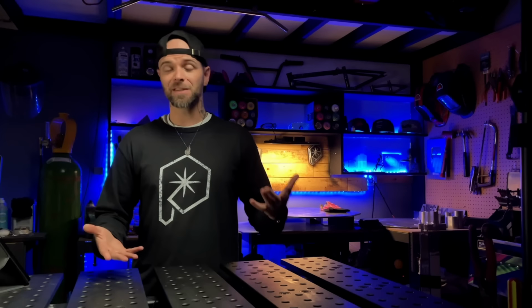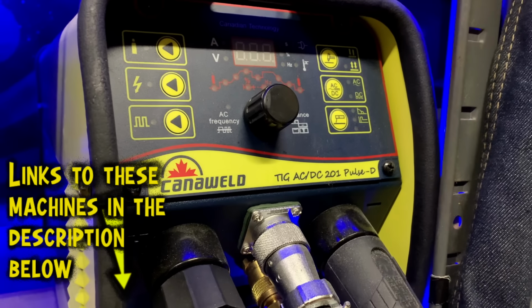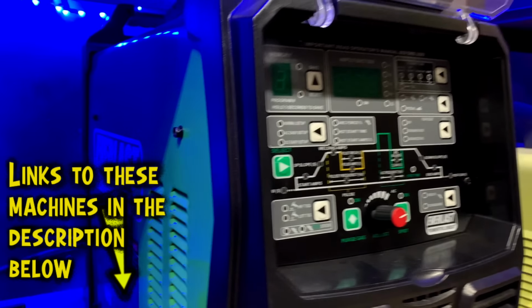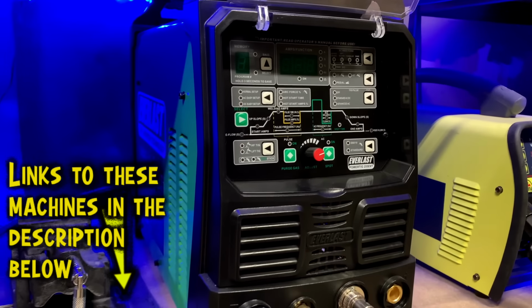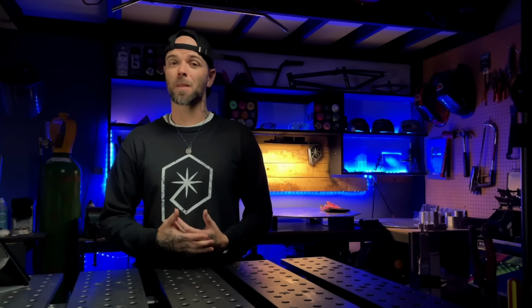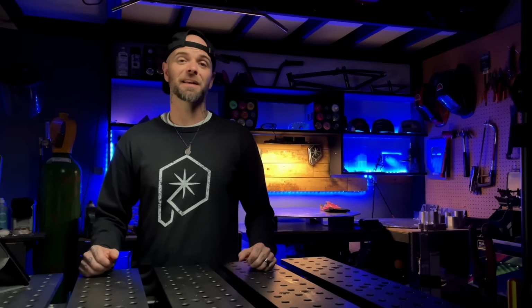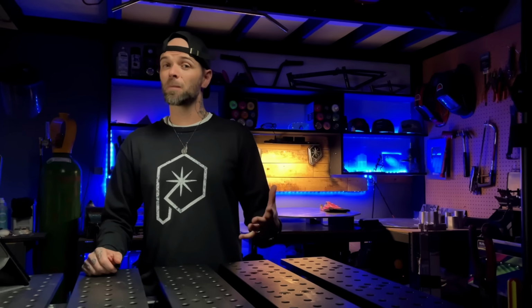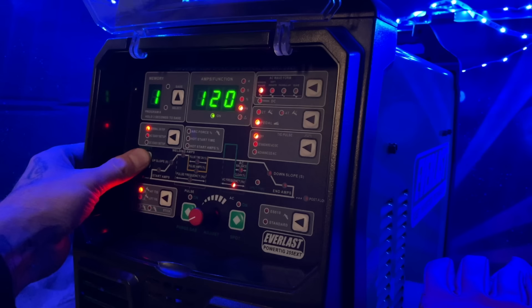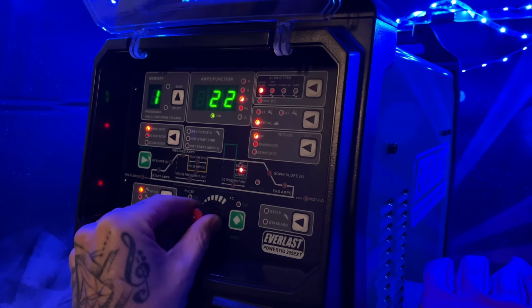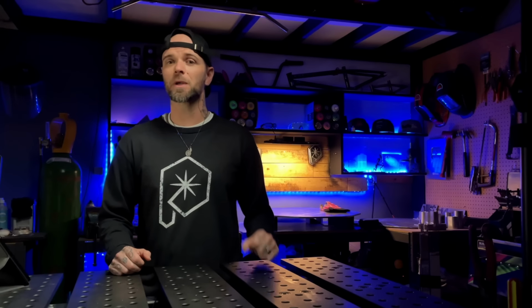So obviously when I'm TIG welding, I want to make sure I run enough heat input into the joint. Obviously, this ensures the best penetration. For the machines I use here in this shop, again, both of these are inverter type machines, I typically find somewhere around 20% on the positive side, 80% on the negative side. This is usually a ballpark that's going to work great. Again, if you want to experiment, you can try increasing and decreasing this, usually by about 2 to 5% per increment. Again, just little squeaks make a big difference.